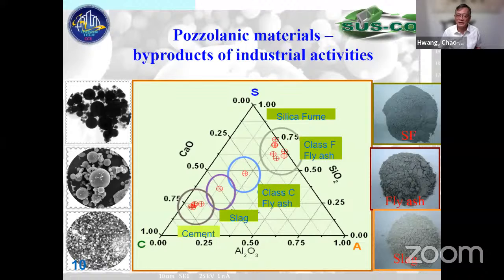And look at the appearance of this one. Silica fume is very small, about 1/100 of the cement particle. Looking at the microscope images by SEM and TEM, the silica fume is here, the fly ash here and the slag here. Next, please.